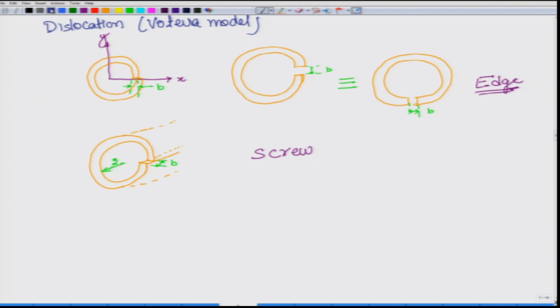Here, just to repeat, there is translation of faces taking place, and another characteristic of translation is that the two faces along which there has been a cut are always parallel. Even in this screw, the two faces are still parallel to each other. So, either they are shifted like this, or like this, or like this, which are the 3 directions x, y and z.